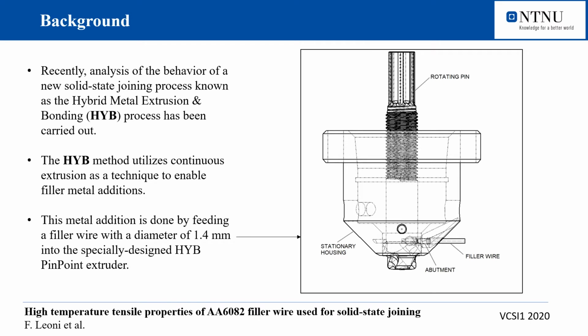The process utilizes continuous extrusion as a technique to enable filler material additions. This metal addition is done by feeding a filler wire with a diameter of 1.4 mm into the specially designed pinpoint extruder, as shown here in the figure. The wire feeding in the process is a crucial part of the joining operation.